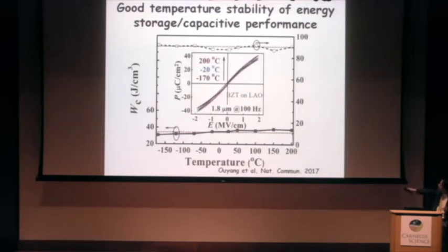And we also did a temperature stability study. We cooled down the film to minus 170 and heated it up to 200 degrees C. You can see the energy changes within about 10%. Efficiency, eventually, there's no change. It's all about 90%.